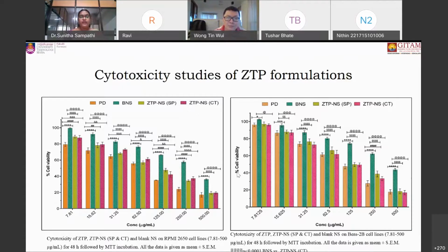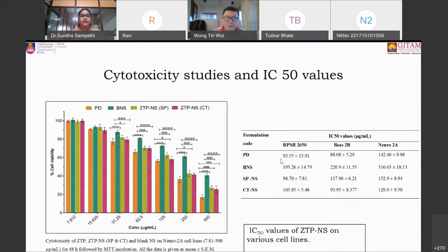So we have checked the cytotoxicity of the other formulation on the bronchial cell lines. And finally, we have also checked the toxicity of the drugs in the neural cell lines, because finally our drug has to reach the brain. When all these cell lines were used and studied for cell viability by MTT assay, where we calculated the IC50 value, we found that the cytotoxicity of all the prepared nanosuspensions was dose-dependent, as seen from the cell viability.